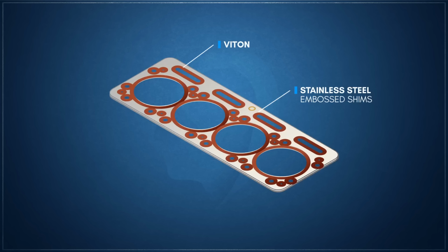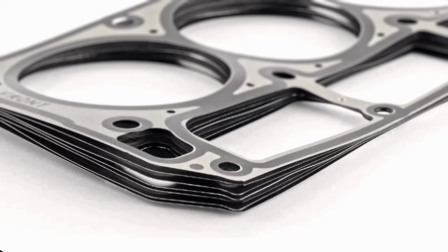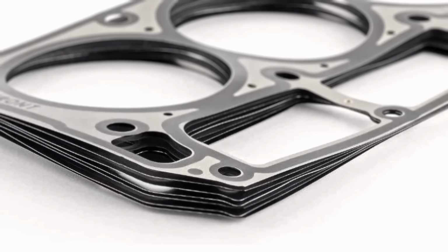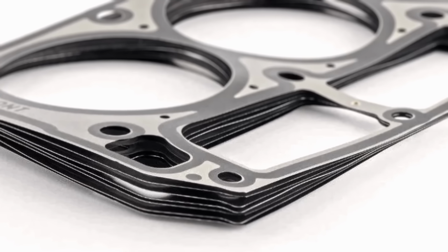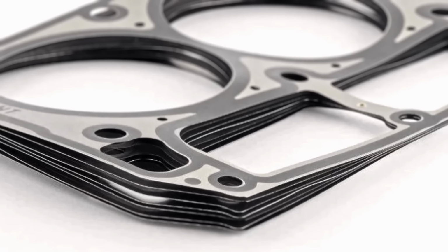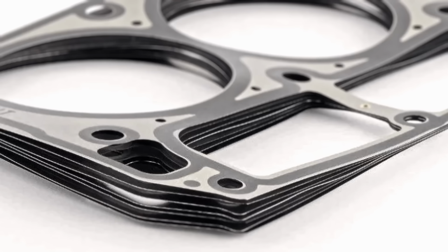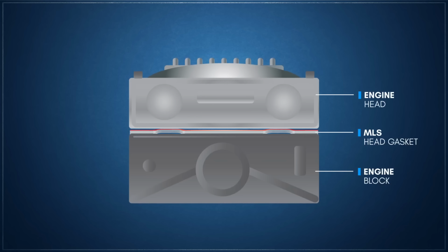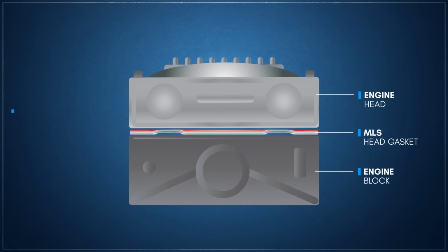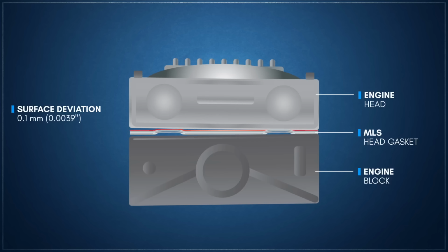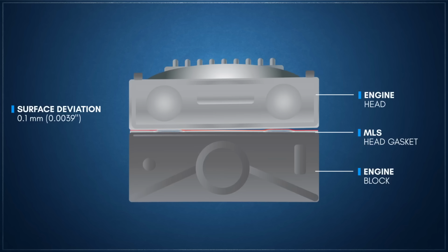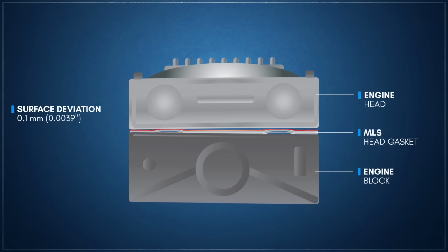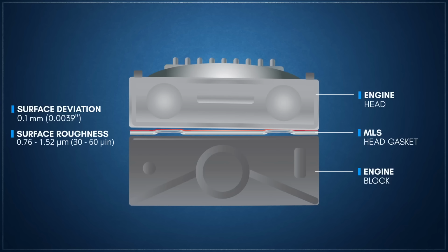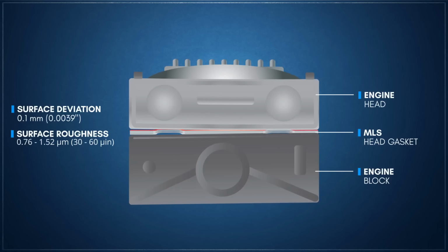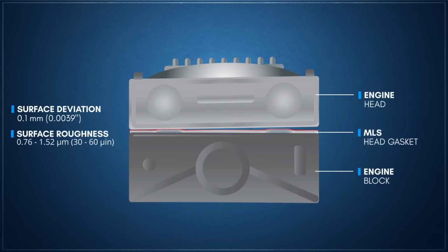Because MLS gaskets are made from layered sheets of steel, they can more easily be manufactured to specific thicknesses and spring rates that allow engineers to more easily adjust a head block gap for specific compression needs or valve train geometries. Their springiness also makes them relatively forgiving in respect to surface flatness. They can easily tolerate surface deviations of up to 1/10 of a millimeter. However, the sealing coating on their outer surfaces generally require a smoother 0.76 to 1.52 micron average surface roughness, or about a grit finish between 180 and 120.